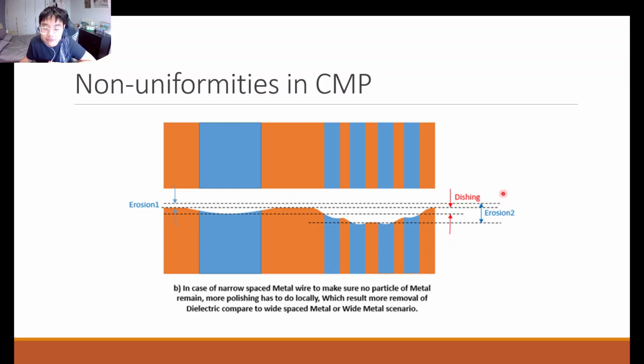And the other non-uniformity, an undesirable feature, is erosion. It is observed that areas where your metal patterns are very close to each other tend to erode faster than areas with fewer of these patterns. For a certain semiconductor wafer, there will be areas where your patterns are closer together and areas where your patterns are further away from each other. So you can see that in the area where the patterns are closer to each other, we have a greater extent of material removal by the CMP process.